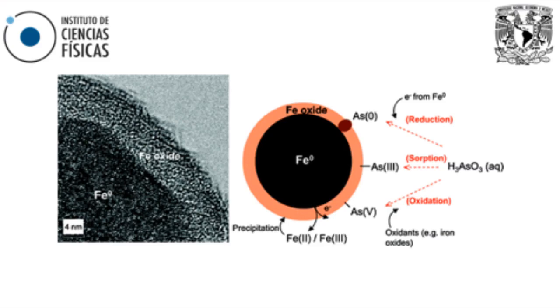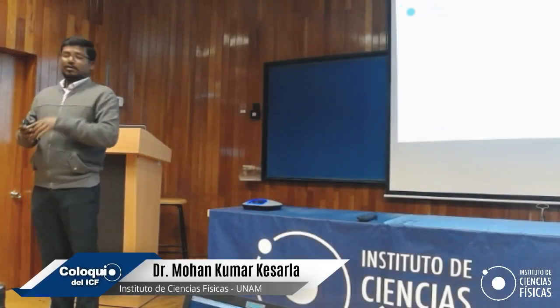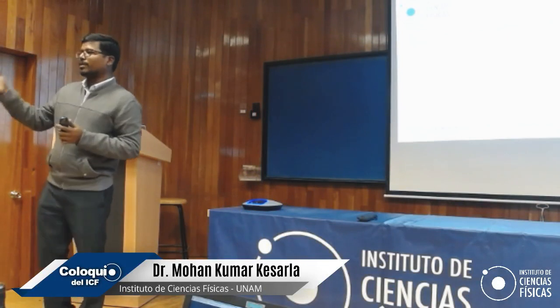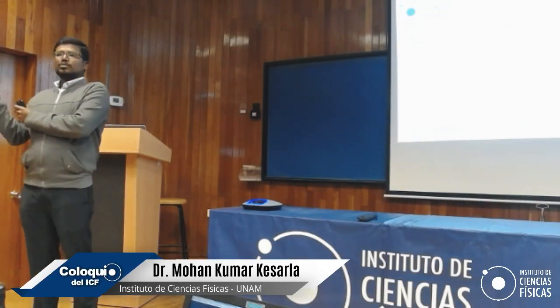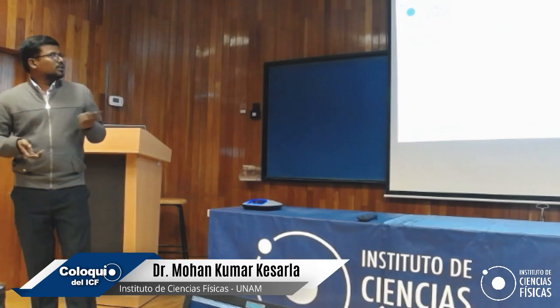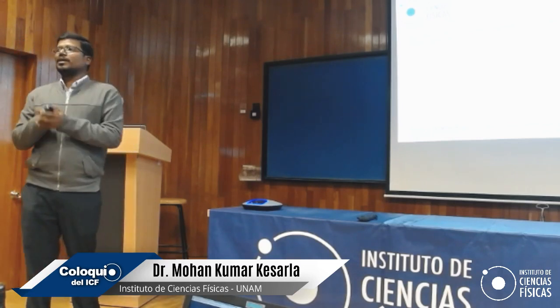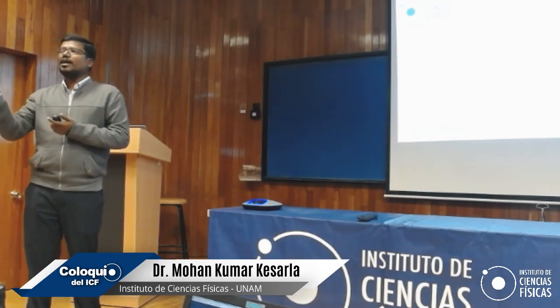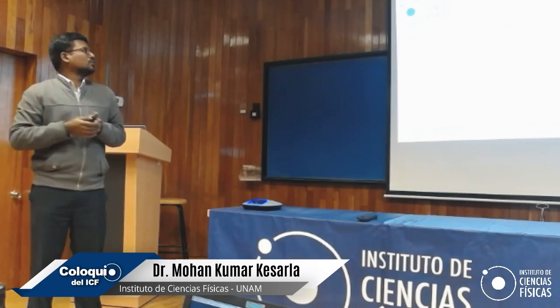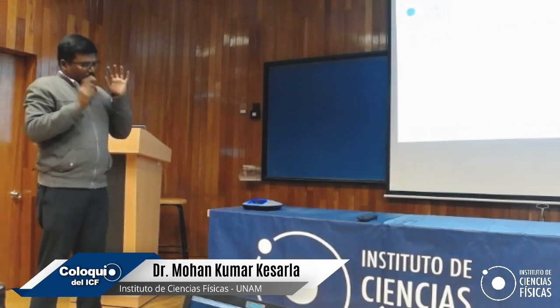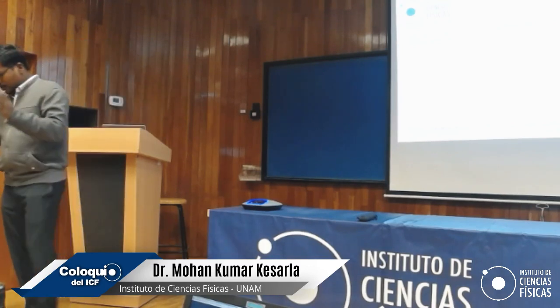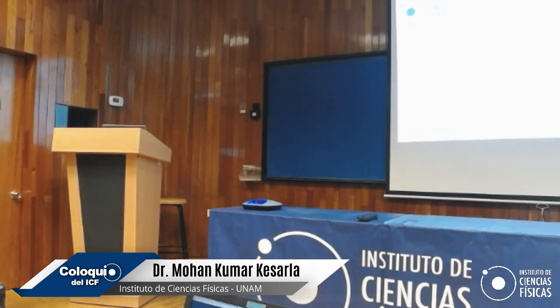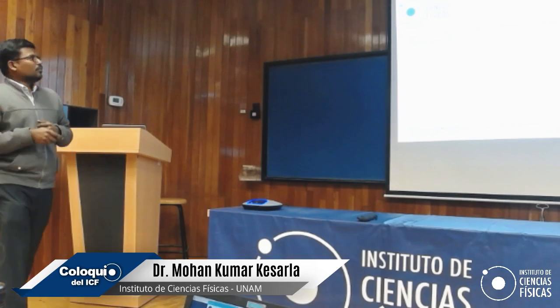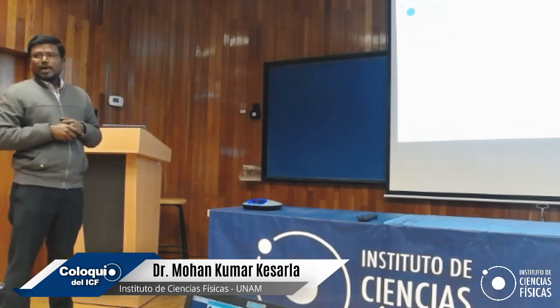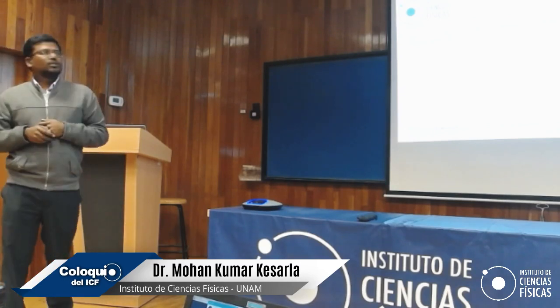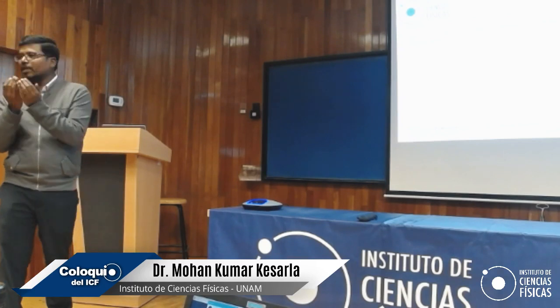After that, we thought about aerial transportation of the zero valent iron. If you want to do something with the zero valent iron, it is very hard to do that. Why? Because it ignites very fast in the oxygen atmosphere. So we thought we want to prepare some zero valent iron we can use. Here we used some iron stabilizers, in order to cap the zero valent iron and avoid the aerial oxidation.